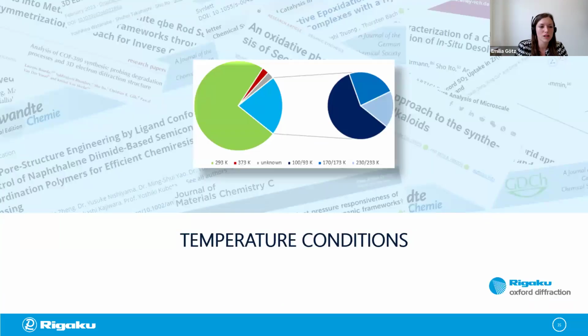And of course, not all of these measurements were performed at room temperature. You can see that a significant part was performed under cryo conditions. And that is because on the one side, the atoms move less at colder temperatures, so the ADPs will generally be better, but also the material will be more stable under vacuum conditions, and the diffraction limit will generally increase. Additionally, solvents or volatile constituents in general can be frozen inside the structure and so be hindered from evaporation in the evacuated instrument column.